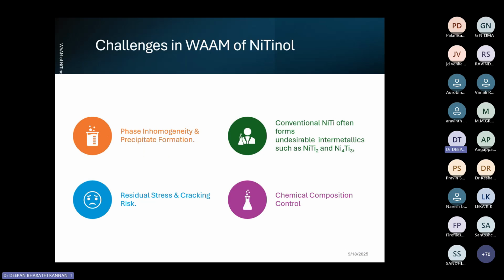Another challenge is that it mainly results in brittle intermetallic phases like NiTi2, Ni4Ti3, because of the non-uniform heating and cooling and various reactions happening during the cooling process. If it is not controlled properly, you may get these brittle intermetallic phases, which in turn will have a negative impact on the mechanical properties as well as corrosion properties, and also the nickel content will get slightly altered. As a result, phase transformation will be affected, then shape memory effect will be compromised. So we may expect the material to change shape on reaching 50 degrees Celsius, but it may change only after reaching 75 degrees Celsius. So that is the challenge we are having, especially with respect to wire cutting manufacturing.